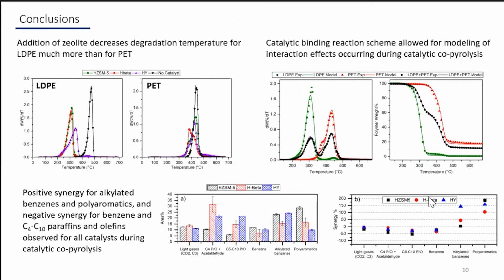So to wrap up the presentation with some conclusions, the LDPE degrades at a much lower temperature in the presence of catalysts than the PET. And there were interaction effects observed during our TGA experiments, and using the reaction scheme which we employed, these interaction effects were able to be captured. And we saw the positive synergy for the alkylated benzenes and polyaromatics, and the negative synergy for benzene and C4 to C10 paraffins and olefins for all of our catalysts.